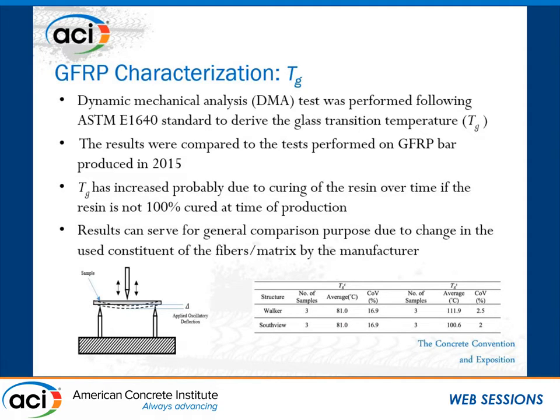And we saw the same type of result in different studies that we performed. The reason we believe that this increase can happen is the additional curing of the resin over time with the exposure to sun and cross-linking of the polymer. So again, this is another sign that this critical parameter of GFRP bars has not been degraded at all after 17 and 12 years of service.